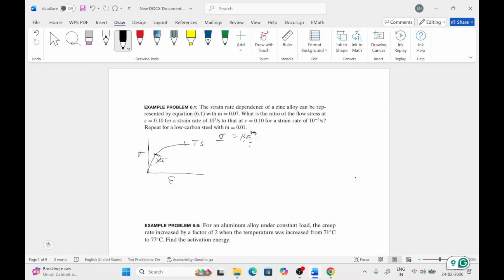So one more criterion comes here. This is at a strain rate, and what if we change the strain rate during testing, or we test the same material with different strain rate values? That behavior is written as sigma equals C times the strain rate, epsilon dot, raised to power m. Here C is some strengthening coefficient, and m is the strain rate sensitivity, meaning how the material behavior changes with the change in the strain rate.